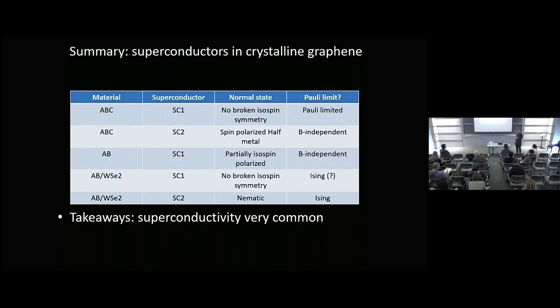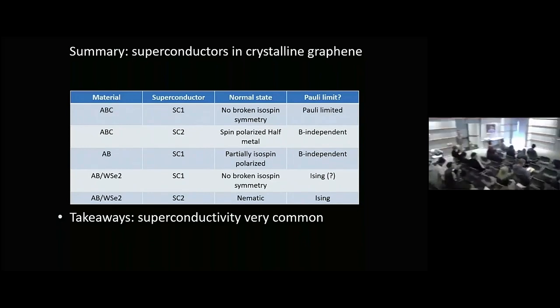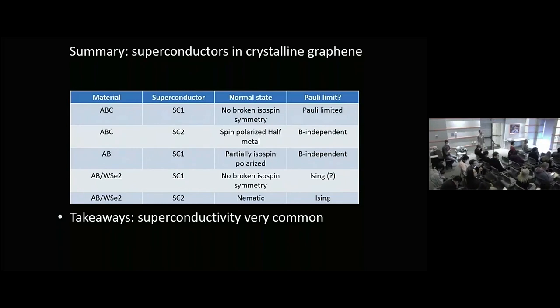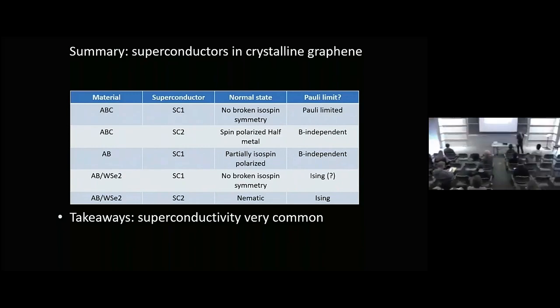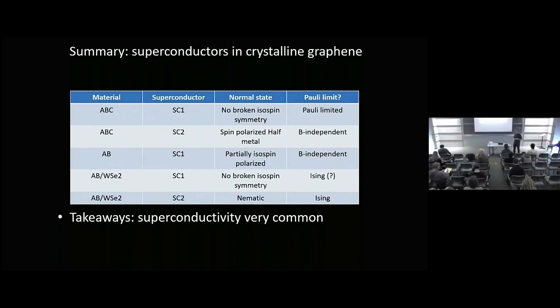How much can you control the screening in these devices? And might that be able to distinguish between some electron-electron interactions? So we have done that experiment very roughly, where we've tried to screen things on, let's say, a 3 nanometer, or I guess the image charges would be like 5 or 6 nanometers away. It didn't make a difference to the ferromagnetism. The sample, for various reasons, didn't have good enough contacts to look at superconductivity. So the ferromagnetism seems to be pretty much a contact interaction type of thing, which I think makes sense. We haven't been able to look at that for superconductivity. We don't have any data on that.